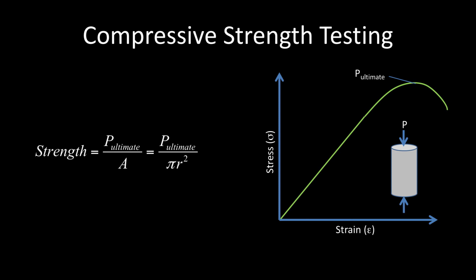diameter cylinders. The reason for this is that the larger diameter specimen is more likely to contain flaws than the smaller diameter specimens. These flaws allow earlier initiation of cracking in the larger specimen. This phenomenon, known as a size effect, is common in many civil engineering materials, with smaller specimens having higher strength and higher variability than larger specimens.